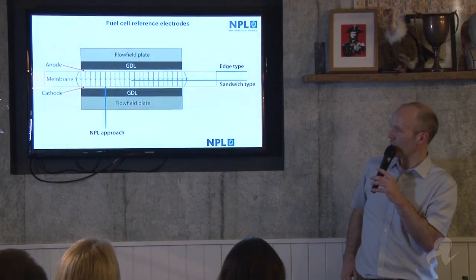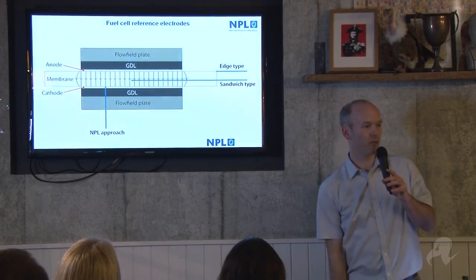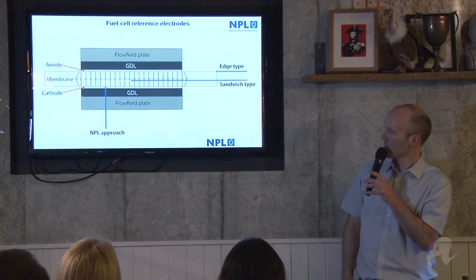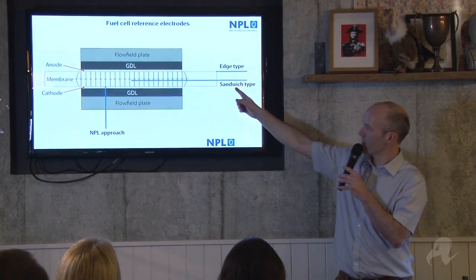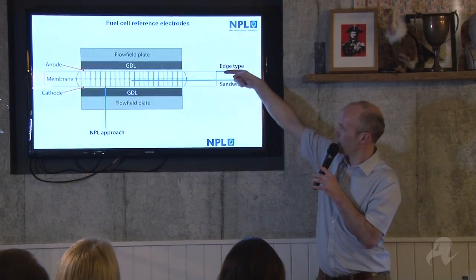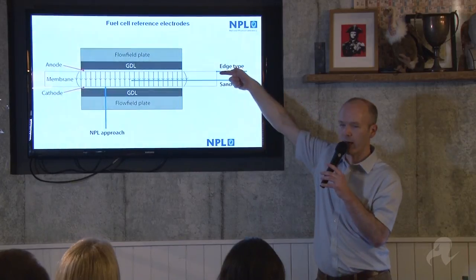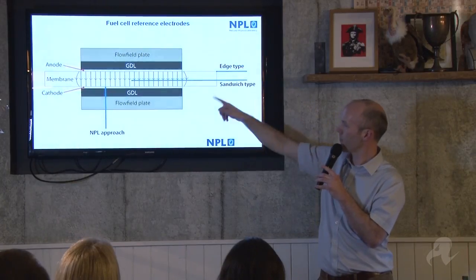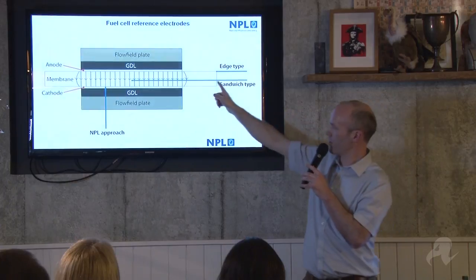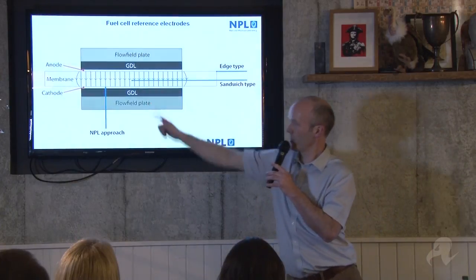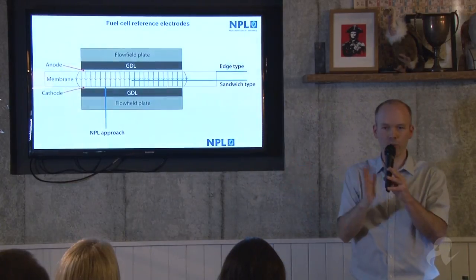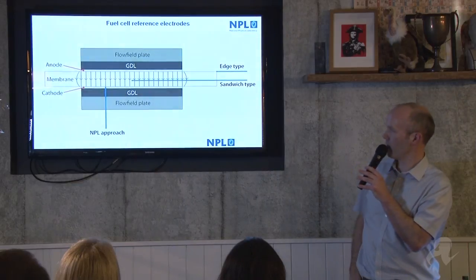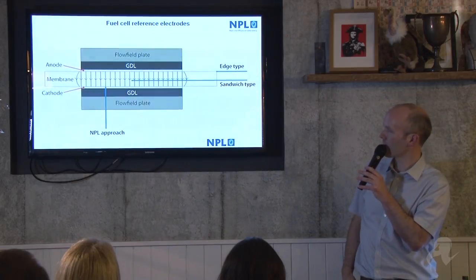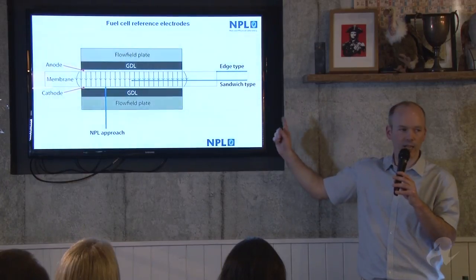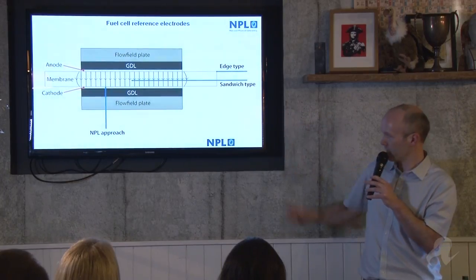Reference electrodes to measure the anode and cathode potential have been used for many decades. And there have been two main types: an edge type, where you just clip the reference electrode onto the edge of the membrane, way outside the cell, and the sandwich type, where you insert a reference electrode right into the middle of the membrane and press two membranes together to give you a sandwich electrode. Neither of these reference electrodes is that reliable.